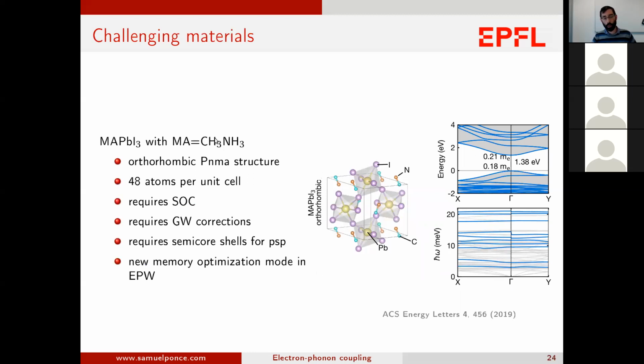If you look at the low temperature phase, the orthorhombic phase, MAPI goes through different phases with temperature. First orthorhombic, tetragonal, and then at high temperature the cubic phase. The well-characterized low temperature orthorhombic structure has 48 atoms per unit cell. You have those lead iodide cages which are tilted, and in between you have those methylammonium molecules.